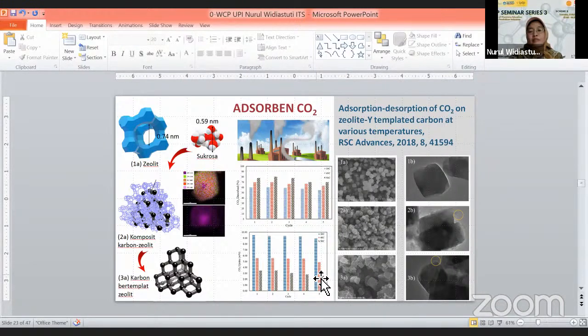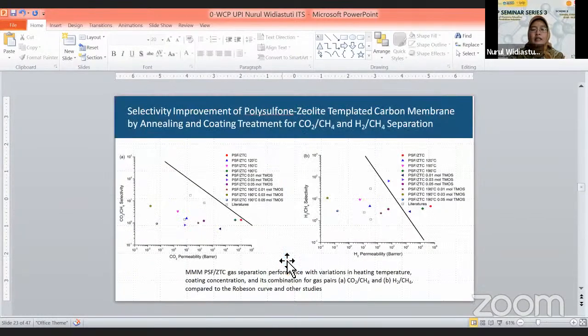We also tried to test the ability of the zeolite templated carbon as a CO2 absorbent before we used it as a filler in mixed matrix membranes. Based on these results, the material can absorb CO2 and also release it, because the interaction between CO2 and the zeolite templated carbon is only a physical interaction in this absorption. So then we continued to use the ZTC as a filler for mixed matrix membranes.